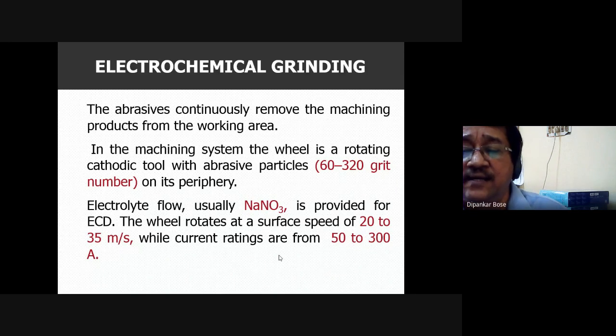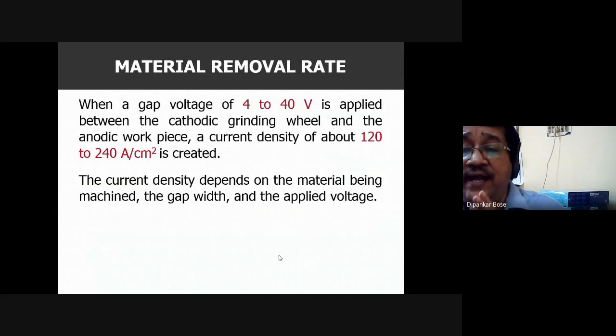and the current rating is 50 to 300 ampere. Now, when a gap voltage of 4 to 40 volts is applied between the cathodic grinding wheel and the anodic workpiece, a current density of about 120 to 240 ampere per square centimeter is created. Really, this is a very wonderful development, this current density. And current density generally depends on the material being machined, the gap width, and the applied voltage.